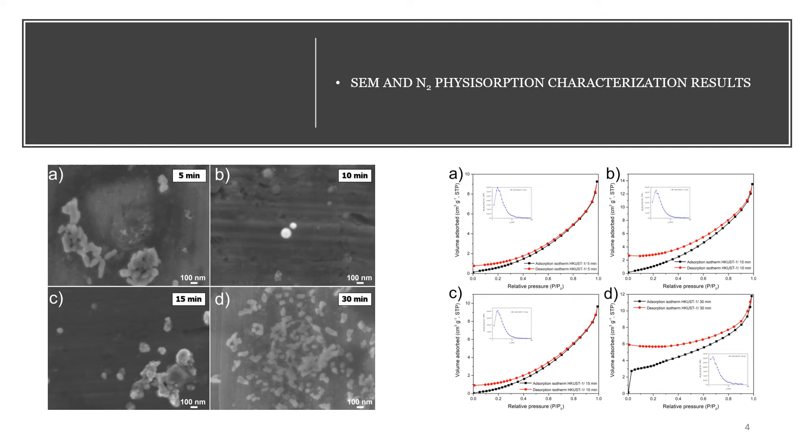After increasing the synthesis time to 15 minutes, the redissolved species agglomerated into bigger crystals, searching for a lower energy state. Consequently, the estimated particle size was higher, 171 plus or minus 33 nanometers.